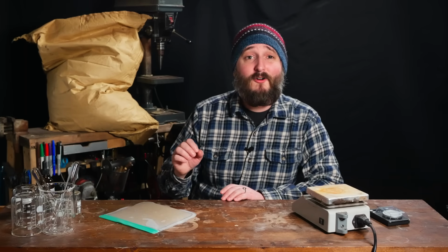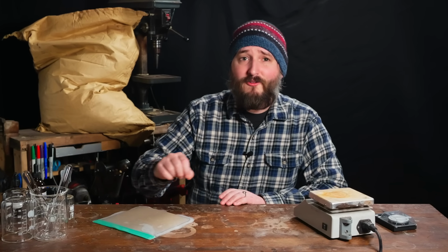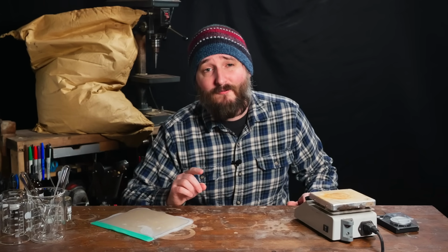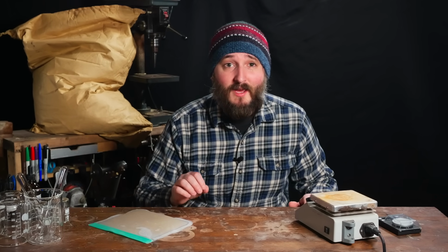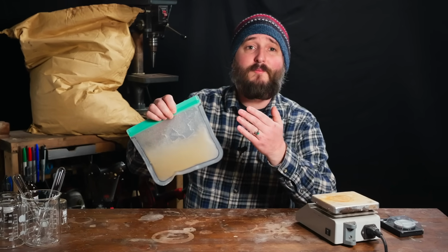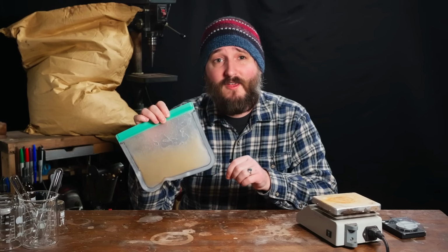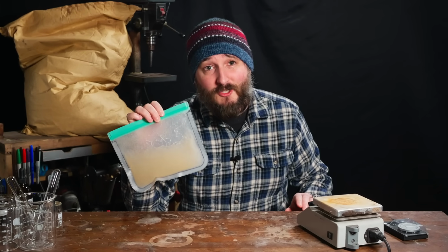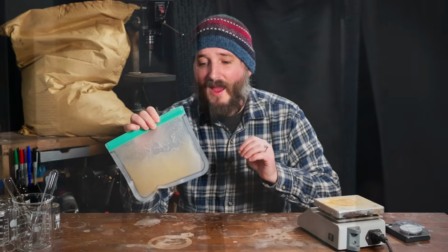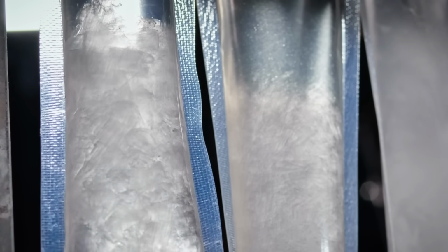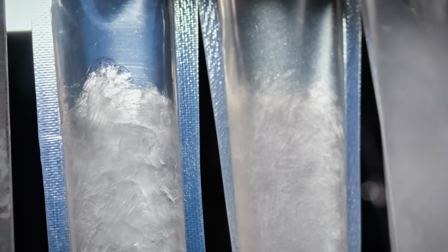In the case of salt-based PCMs, that is, phase change materials like this sodium sulfate variety, I was aware of one problem that these can have called phase separation, where crystals settle to the bottom over time, which reduces the effectiveness for thermal storage. What I didn't realize is how big of an issue this is, and how much research has gone into attempted solutions.